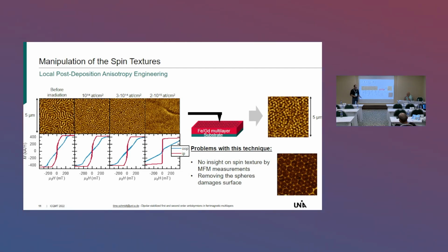There's approximately 3 nanometers of film they just rip off when they get removed, because they glue a little bit to the sample. And for membranes, it's not suitable because you would damage your membrane and you wouldn't see anything. So the question is, can we realize it another way? And now comes the outlook.